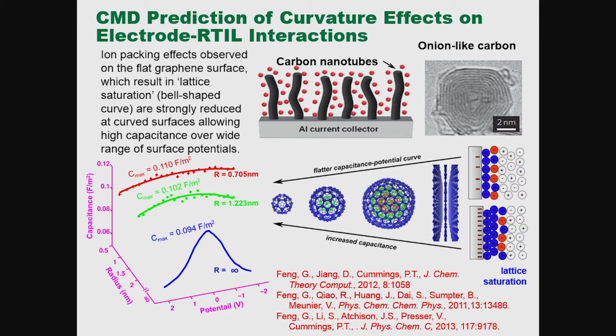We've looked at surface curvature effects computationally. Ionic liquids are big, and because of pi-pi stacking interactions with graphene, they overcompensate surface charge. Quite often the cations are strongly adsorbed, and so on a flat surface you get packing problems—excluded volume problems that limit the capacitance as a function of surface potential.